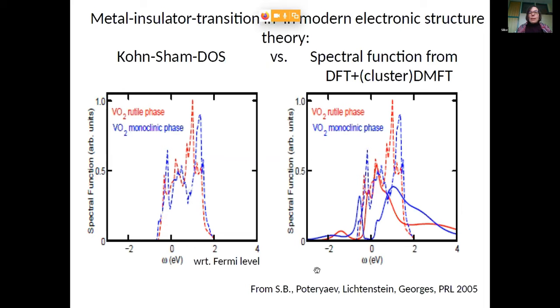What we did, and that is actually quite old calculations in collaboration with Sasha Poteryaev, Sasha Lichtenstein, and Antoine Georges, were dynamical mean field calculations. I will tell you in a second what that means. I will first show you the results and discuss what we see. Here in red is the metallic phase, and in blue the insulating phase. What I mean by this is that we did the DMFT calculation for the given crystal structure of, on the one hand, the rutile structure, and on the other hand, the monoclinic crystal structure. And that is, again, in comparison to the DFT density of states in the background.